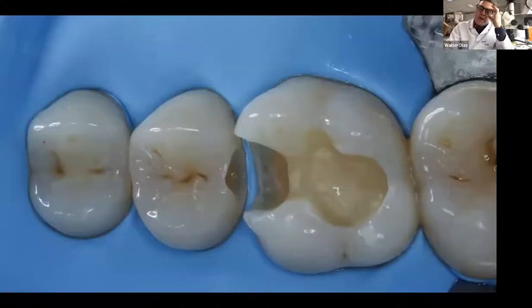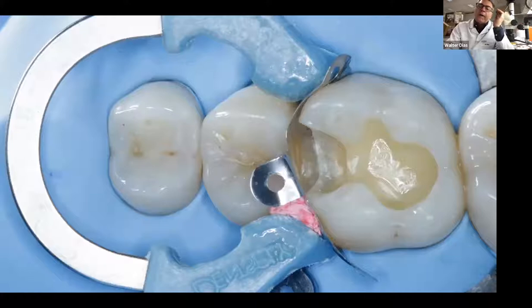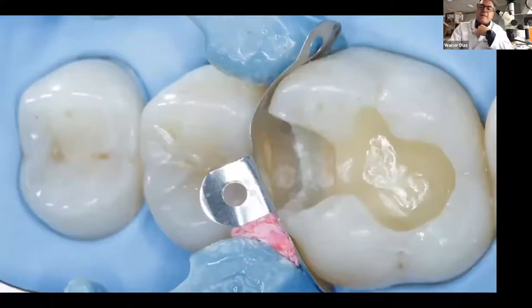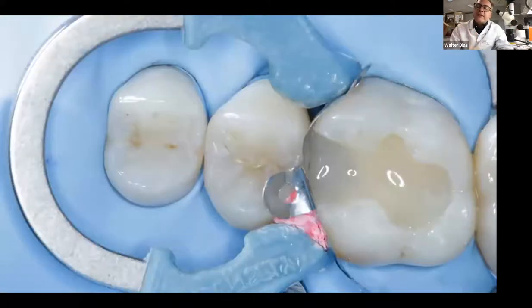So in this case, we have the case ready to go. This is direct, okay, but I'm going to show you the application of the immediate dentinal sealing on this case before the composite is applied. So what we did here is we made a good adaptation using a Palodent matrix system. And then after the application of the adhesive and light curing the adhesive, we seal the dentin with a layer of SDR.